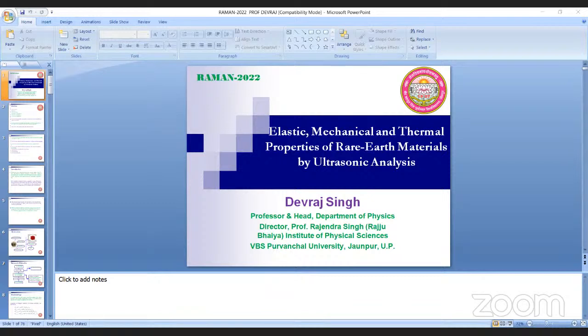Another criterion for finding whether the material is soft or hard, brittle or ductile, we use the Pugh ratio or Pugh indicator. Pugh indicator is bulk modulus divided by shear modulus. If this value is less than 1.75, then the material will be brittle. Otherwise, if this is greater than 1.75, then the material will be ductile. And this is the condition for central force. If this condition is fulfilled by the material, then the material is under central force. Otherwise, it is not. For non-central force, the condition is given as 0.23 to 0.24.